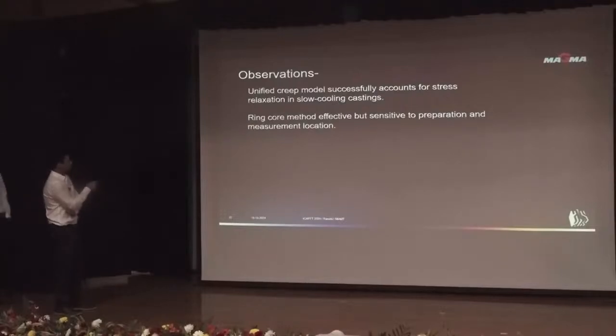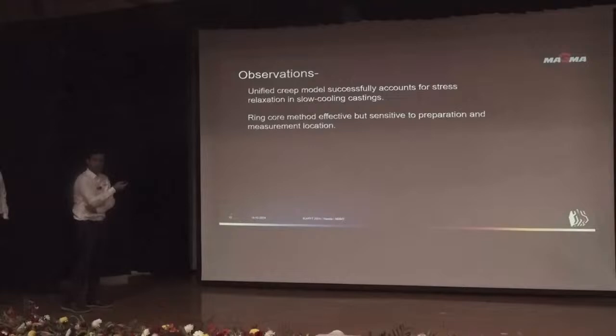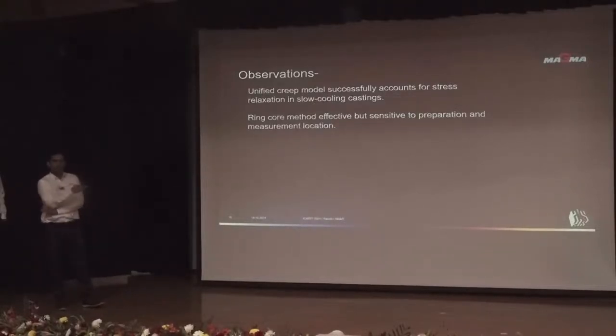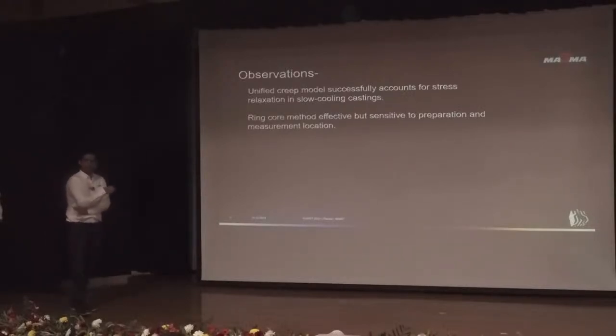So what were our observations? The unified creep model successfully shows us what the relaxation is and how it is going to happen in large castings. The ring core method is very effective, but very sensitive to preparation and measurement location. So we have to identify the locations before doing that.